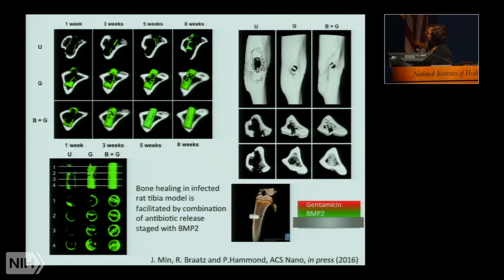And what we've been observing is that the combination of BMP2 and gentamicin sulfate leads to a much more rapid regeneration of bone around the implant. Furthermore, if we look at the micro-CT, we can see the resorption that occurs in the untreated sample. We can see that with just gentamicin sulfate, bone is enabled. It can begin to regenerate, but it's not quite as complete. And with the combination, we're getting a much more solid slug of regenerated bone present in these systems.